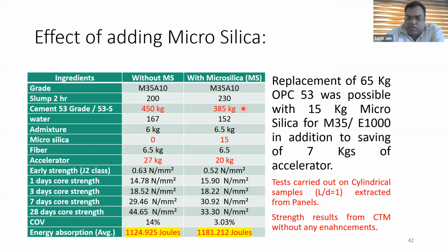Now see the interesting change. We have added 15 kgs of microsilica. We reduced the cement by almost how much? 50 and 15, 65 kgs. We have reduced the accelerator dosage by 7 kg. So all this is saving, this is money saved. And still the energy which we are getting is more than what we got earlier.